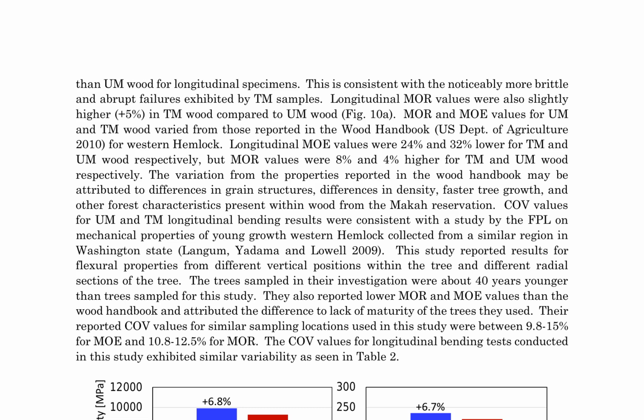The modulus of elasticity, MOE, values for TM and unmodified wood were found to be 24% and 32% lower, respectively, compared to the values reported in the Wood Handbook for Western hemlock. However, MOR values were 8% and 4% higher for TM and unmodified wood, respectively, compared to the Wood Handbook values. These variations are attributed to differences in grain structures, density, faster tree growth, and other forest characteristics present within the wood from the Makah Reservation.